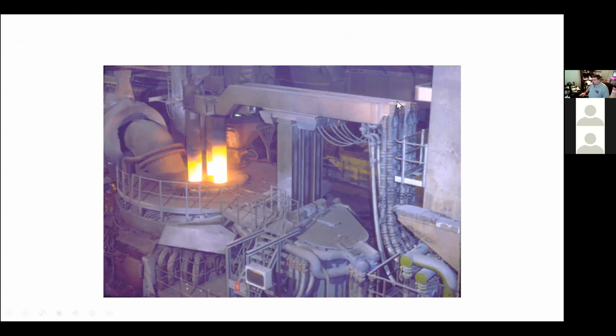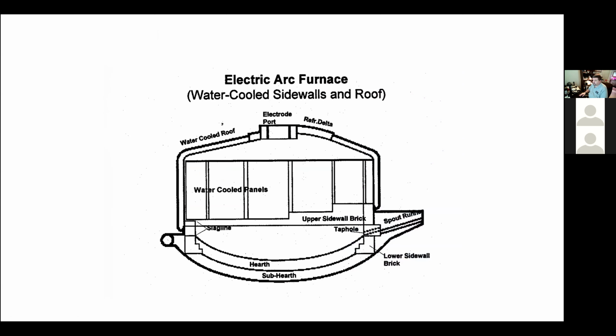So here you can see an actual industrial electric arc furnace from one of my clients. And you see that the electrodes are clamped. We're holding an electrode attached to each of the three arms. We have these masts which can move up and down hydraulically, used to regulate the power input to the furnace. And the graphite heats up enough that it's glowing white hot. In fact, the temperature in the electric arc itself is probably on the order of 8,000 to 12,000 degrees. Very, very hot. This just shows you the main components again, the furnace bottom, which is refractory lined, and the water cooled panels.